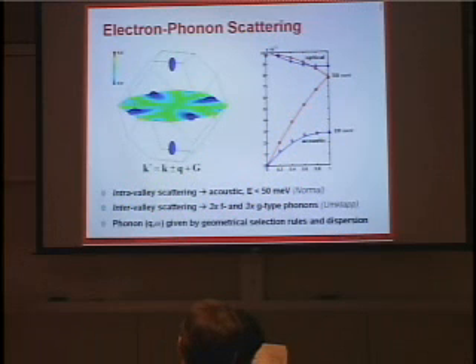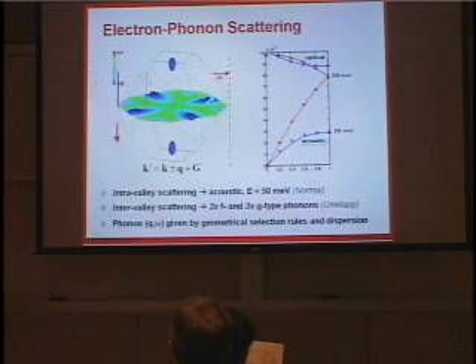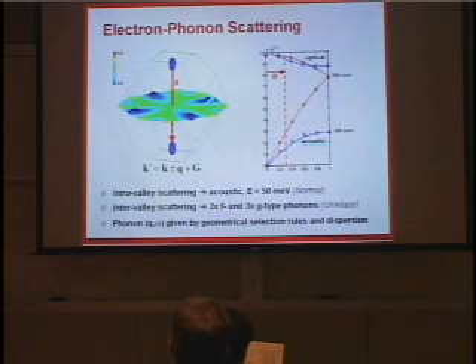Again, we've got the 6 equivalent energy bands in silicon, which is where most of the transfer takes place. On the right, I have my approximation of the phonon dispersion. And as I was saying earlier, for electron energies below 50 milli-electron volts, they tend to scatter mainly inside one of these valleys. That's called intra-valley scattering. They tend to scatter with the acoustic phonon modes. And for electron energies above 50 meV and some below, they tend to scatter between these valleys.